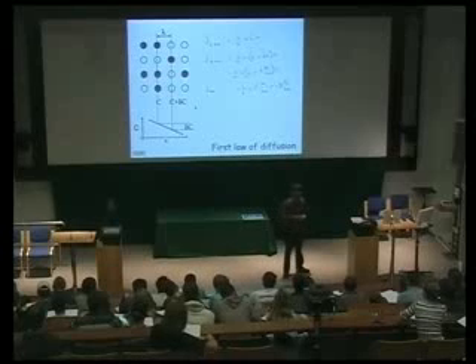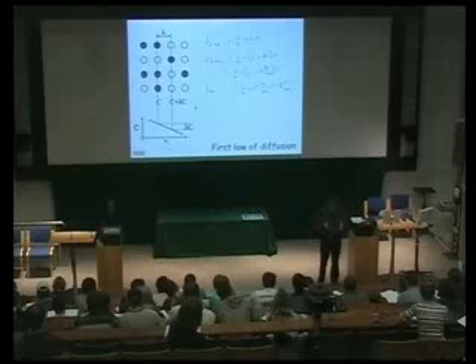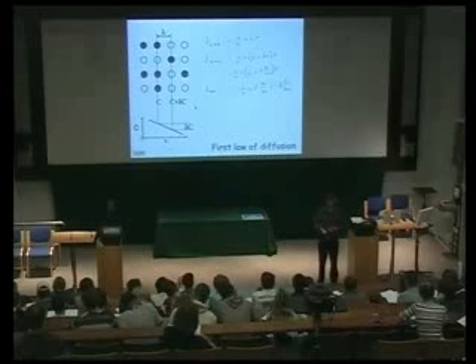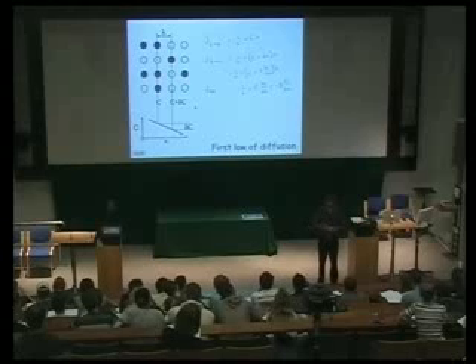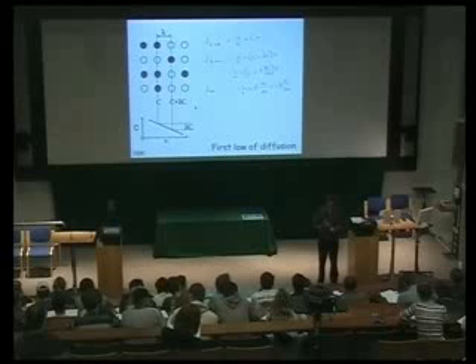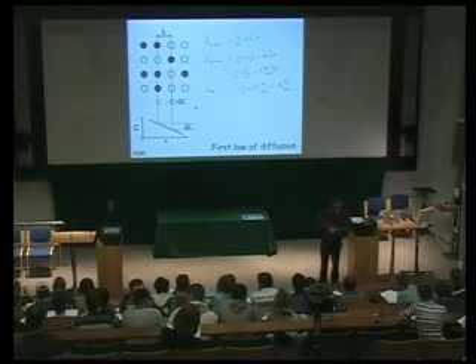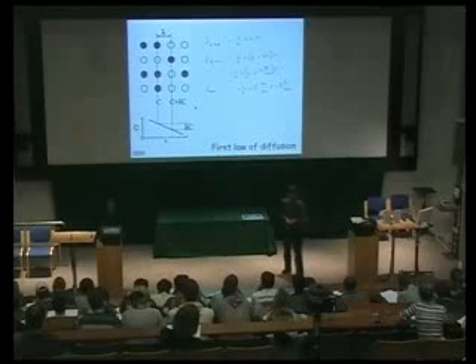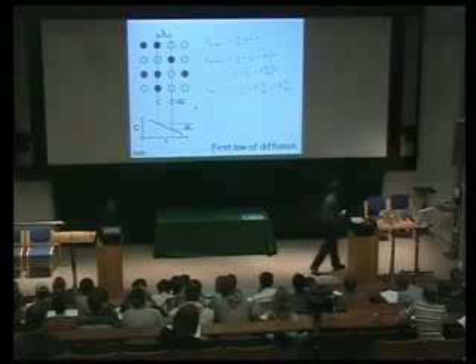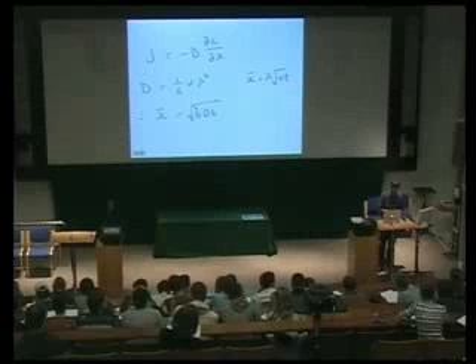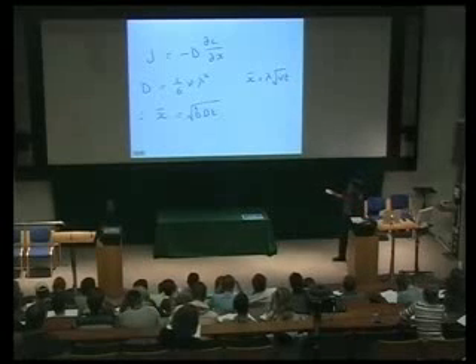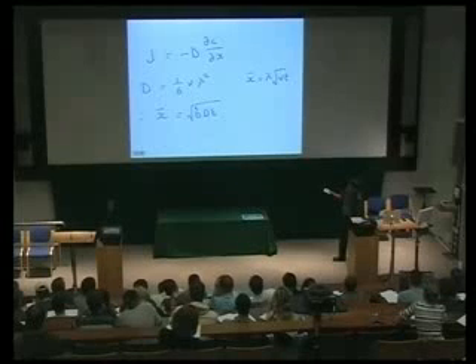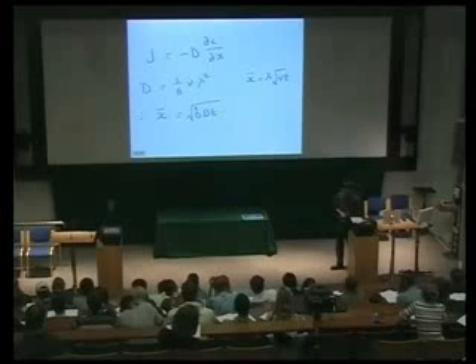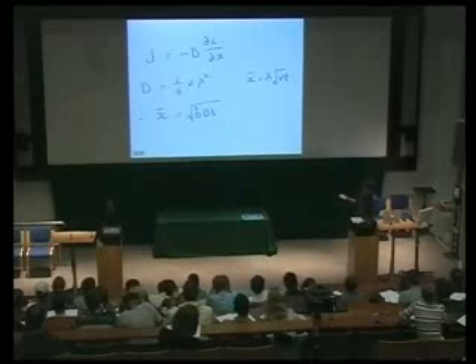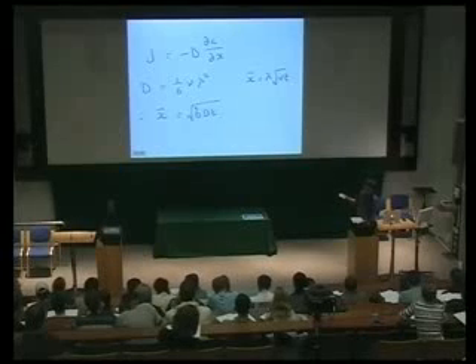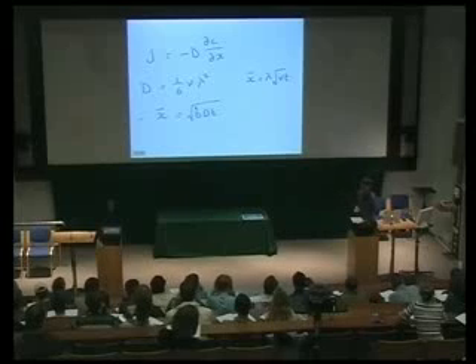Okay? Now, this is known as Fick's first law of diffusion, that the flux, which is the number of atoms per unit area per unit time, is proportional to the concentration gradient multiplied by the diffusion coefficient, and there's a minus sign because this gradient is negative here. Okay? So this is Fick's first law of diffusion. And it's expressed usually in a simple form that we have the flux, the diffusion coefficient, and the gradient. And I absorbed the jump frequency and the jump distance and the 1/6 term into this single parameter d.